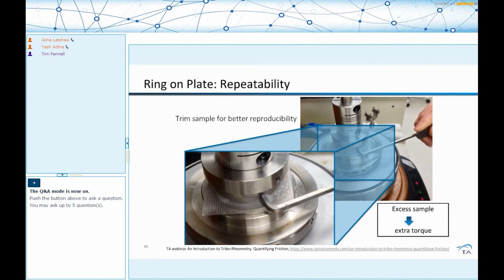And that is where the power of the rheometer is, that when you're using a ring on plate kind of a setup, you want to make sure that you trim the excess sample, because that excess sample can cause some extra drag and you don't want that affecting your measurements. This is very similar to the conventional rheological measurements as well. And again, we talk about this in the first part of the webinar, or the link below, the first webinar we presented on Tribo-Rheology.